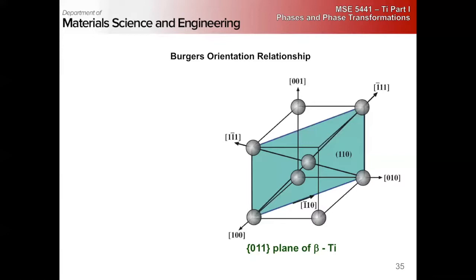Yes. So this was the point I was going to make. It's very challenging in steels because there isn't a fixed orientation relationship, right? It's somewhere between Kurdjumov-Sachs and Nishiyama-Wassermann, and it's not constant anywhere, and the martensitic transformation is accompanied by plastic deformation. In titanium, this problem was actually solved quite some time ago because this Burgers orientation relationship is always observed and it's always dead on, right? There's no variability, there's no variability in it.